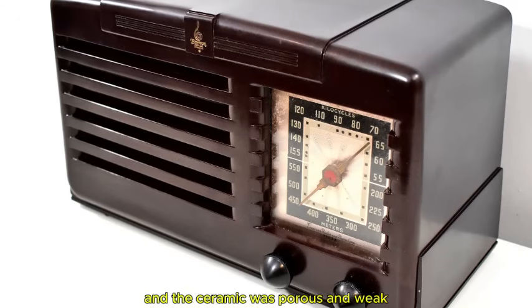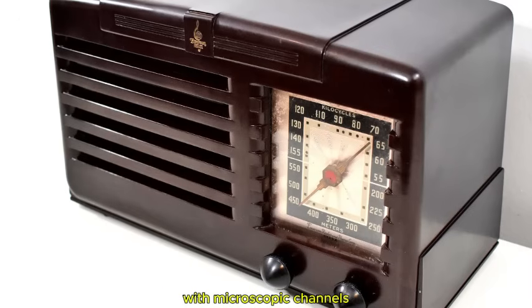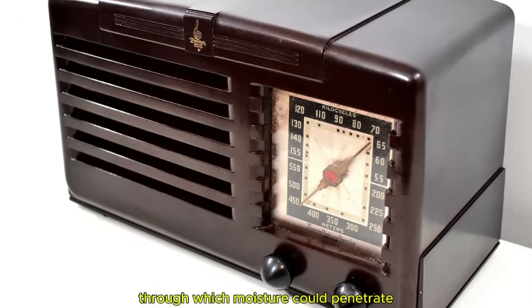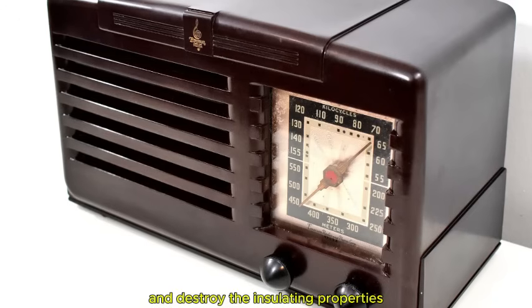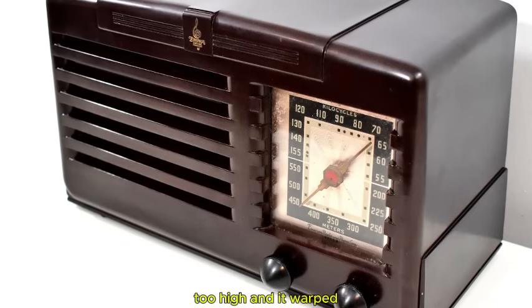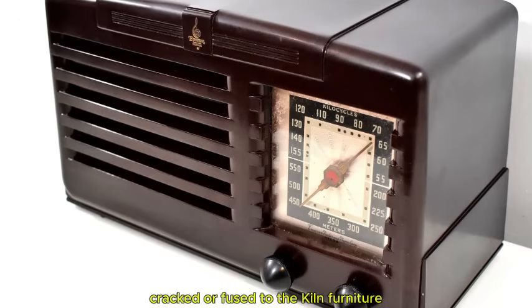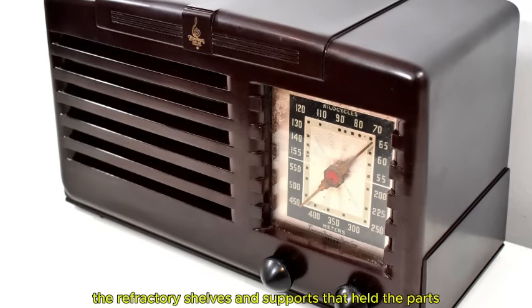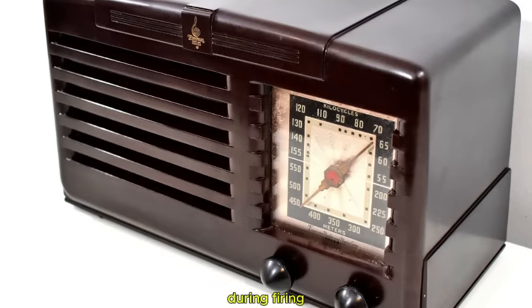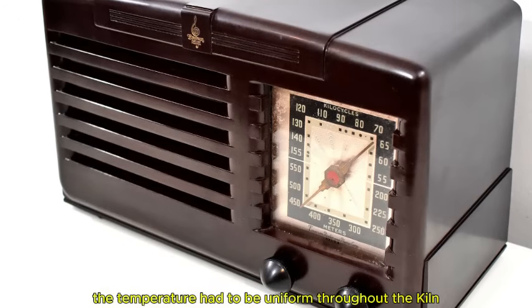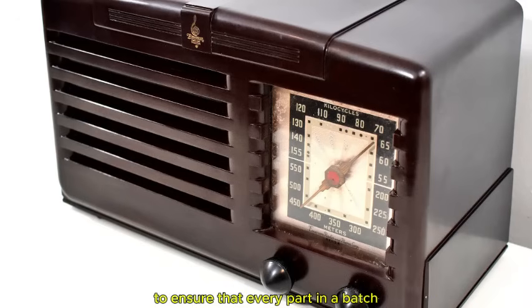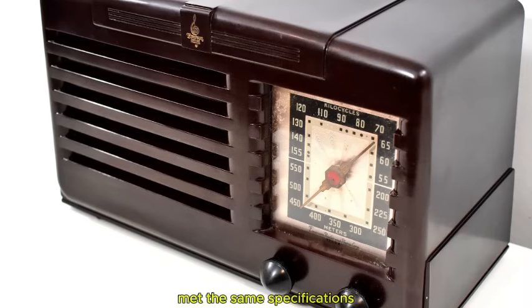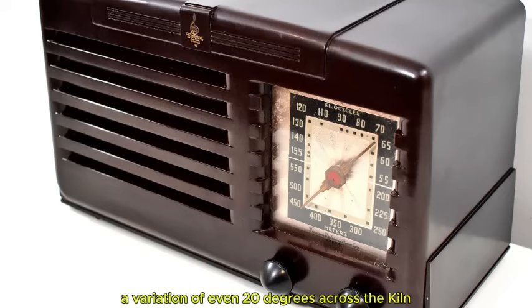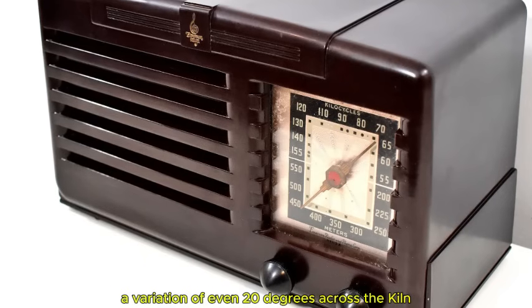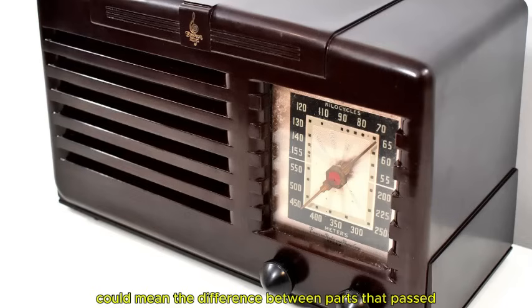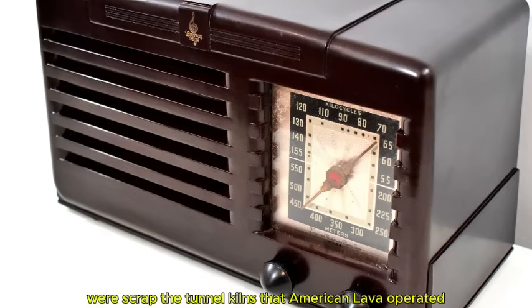Too low a temperature and the ceramic was porous and weak, with microscopic channels through which moisture could penetrate and destroy the insulating properties. Too high, and it warped, cracked, or fused to the kiln furniture, the refractory shelves and supports that held the parts during firing. The temperature had to be uniform throughout the kiln to ensure that every part in a batch met the same specifications. A variation of even 20 degrees across the kiln could mean the difference between parts that passed military inspection and parts that were scrap.